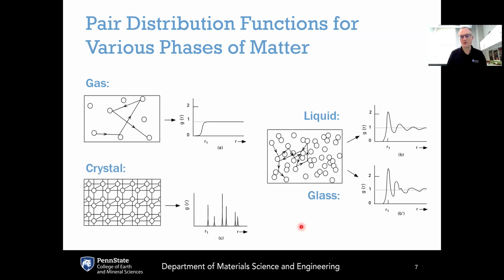Now, what do some of these pair distribution functions look like for various phases of matter? Let's start with the crystal here, the crystal in the lower left corner. The structure of the crystal consists of unit cells. The unit cell tells you the basic structural unit that gets repeated in all 3 directions. And what this means is that for a crystalline material, the atomic positions in principle are perfectly well known and perfectly well defined. So if we plot the pair distribution function for a crystal, what you'll see is that there are very sharp peaks. These sharp peaks occur at well-defined positions, and the intensities of those peaks would tell you how many atoms are being found at those various positions.